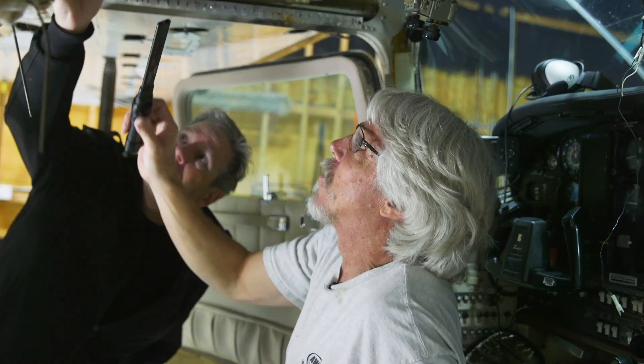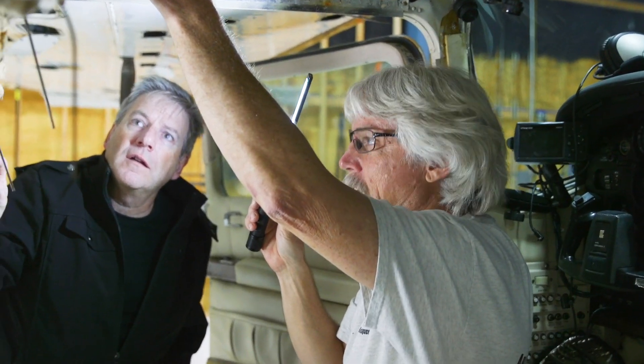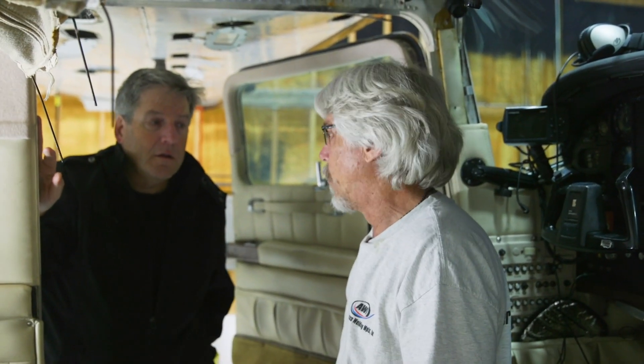The problem with a lot of aircraft is with that foam in there. We've had other aging aircraft issues as well. They used a lead blanket material, lead-impregnated. Some of the glues they used back in the day cause corrosion — they're just corrosive by nature. When you introduce moisture, such as from an air conditioner or just sitting outside on a ramp, oxidation, salt air — any of those things cause corrosion. It's the right compounds and combination that causes these issues.